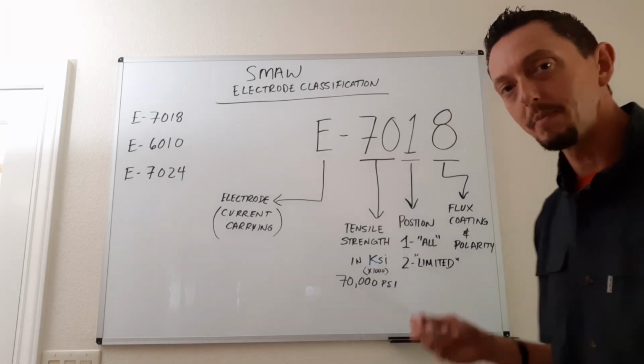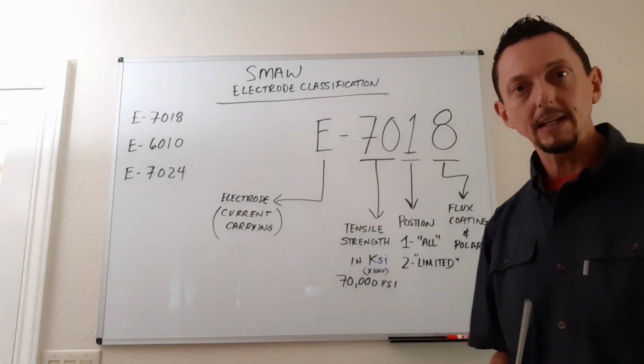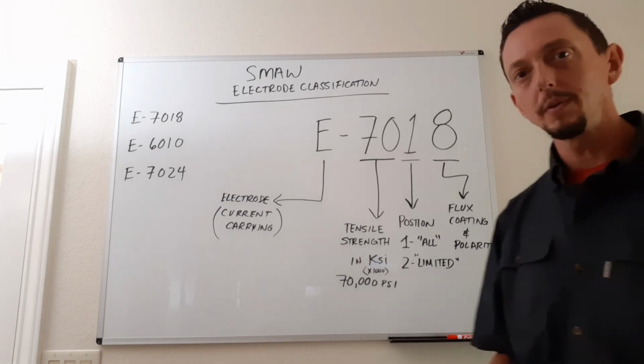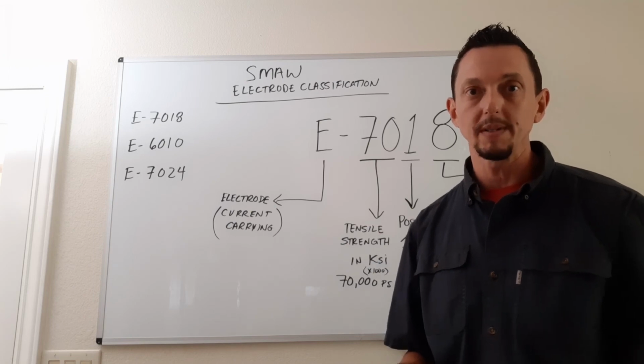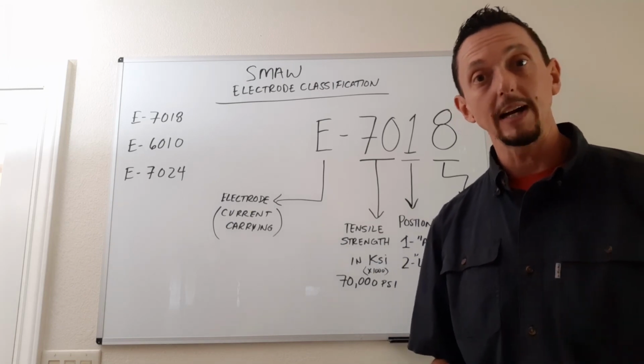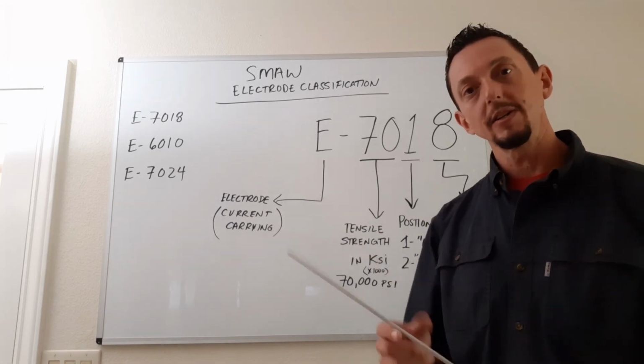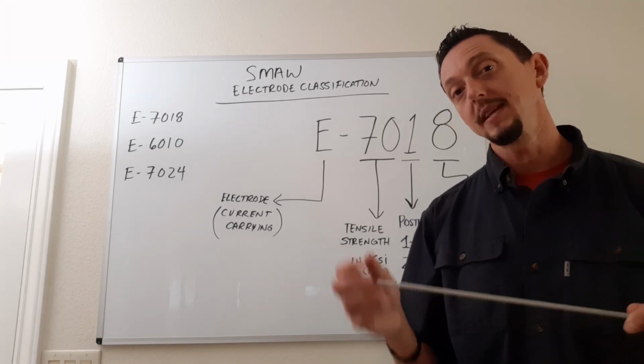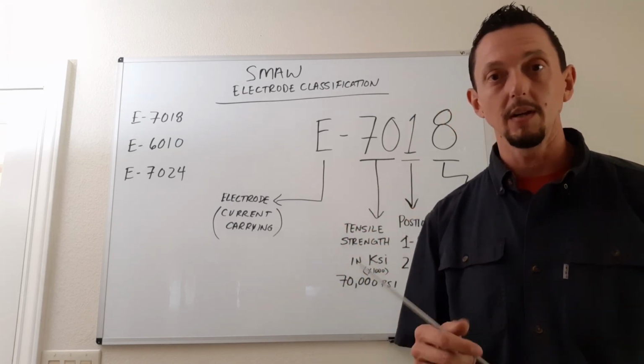Now another option would be a 2, which would be a limited position, which are typically only going to be used in flat and horizontal position because that's a fast fill electrode. This would be considered like a fast freeze electrode, which means that the weld pool freezes quickly so you can use it in all positions.